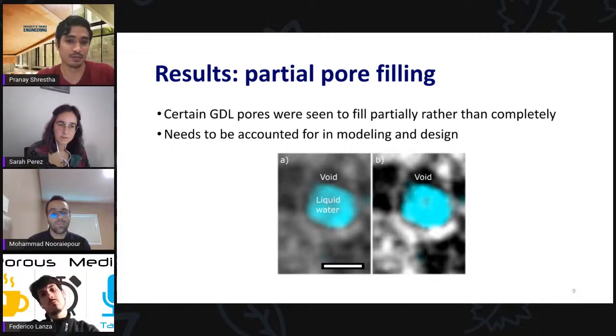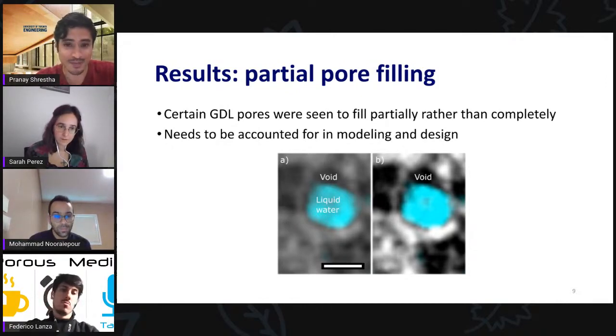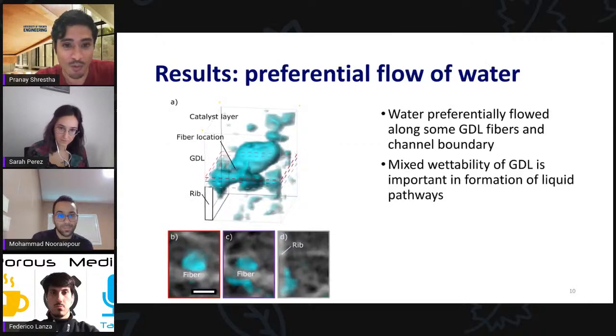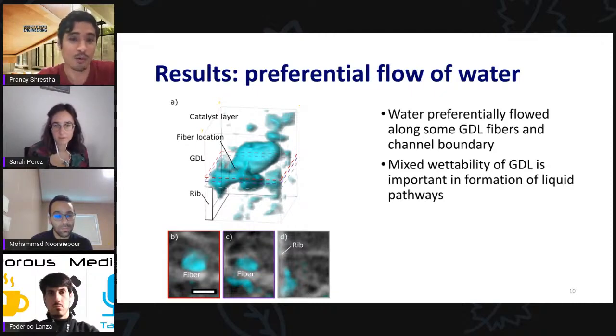The reason for partially filled pores here was first the heterogeneous pore structure and mixed wettability in the GDL. We found more evidence of mixed wettability, where around certain GDL or porous medium carbon fibers and the channel boundaries, we found water preferentially flowed along them. That gave us some evidence that mixed wettability did actually impact how water distribution is formed in the fuel cell.